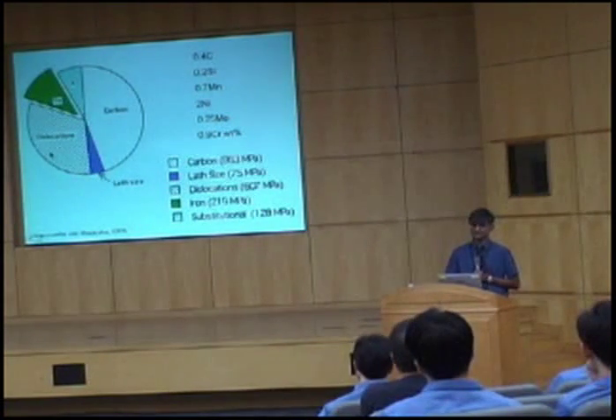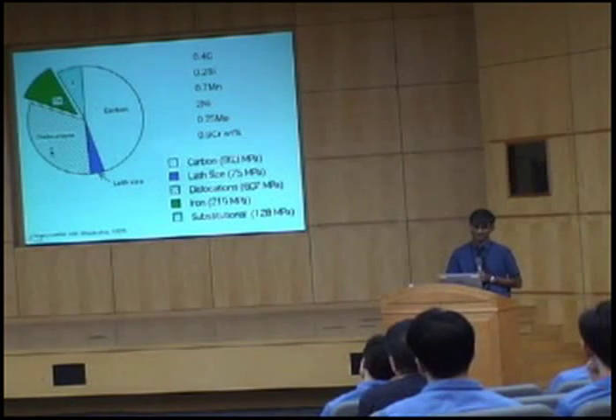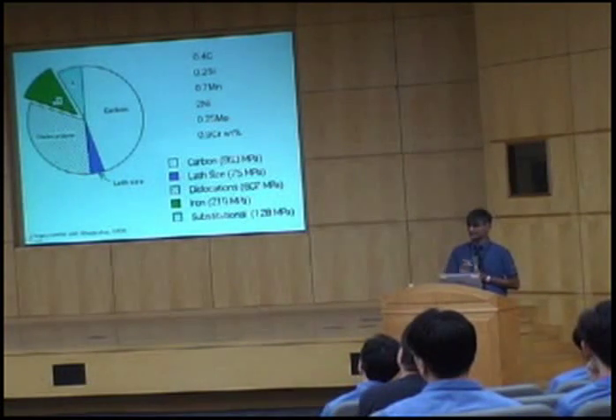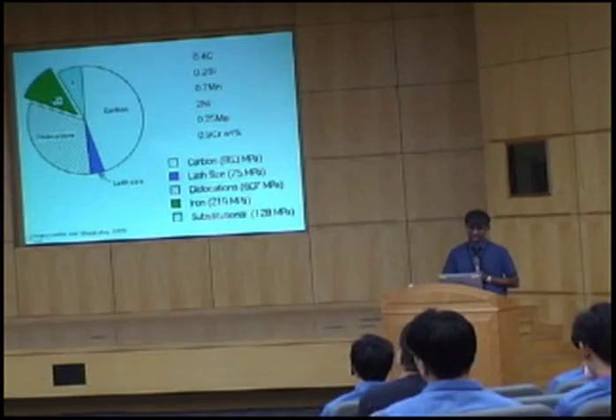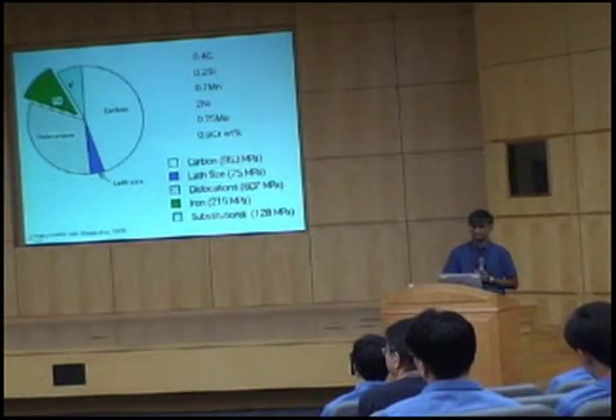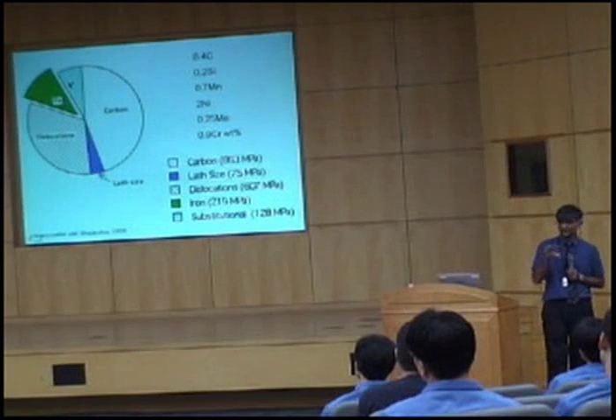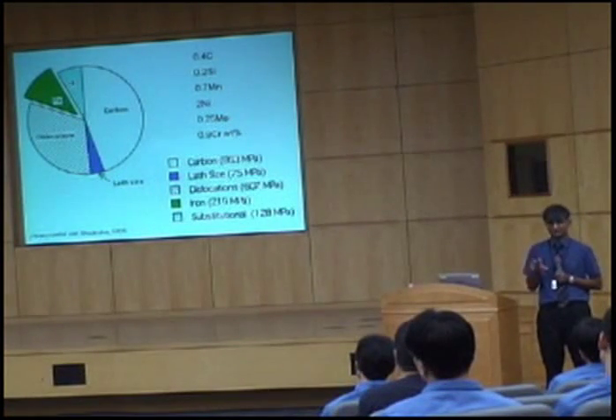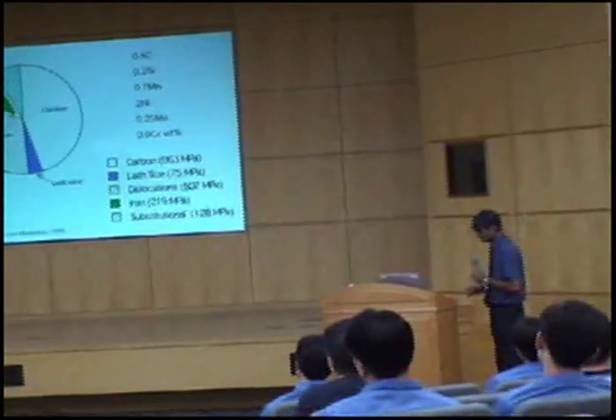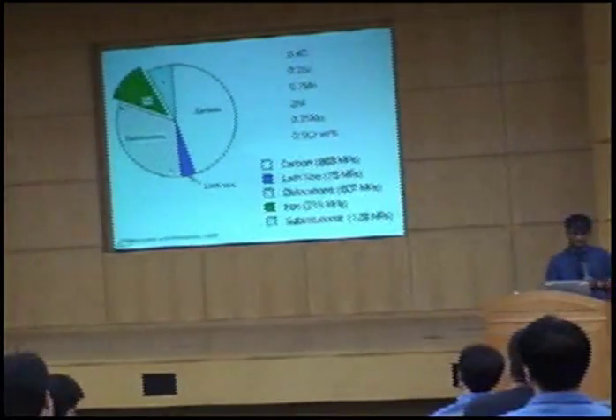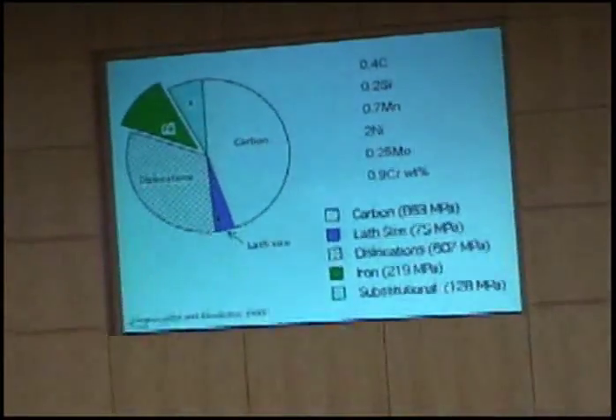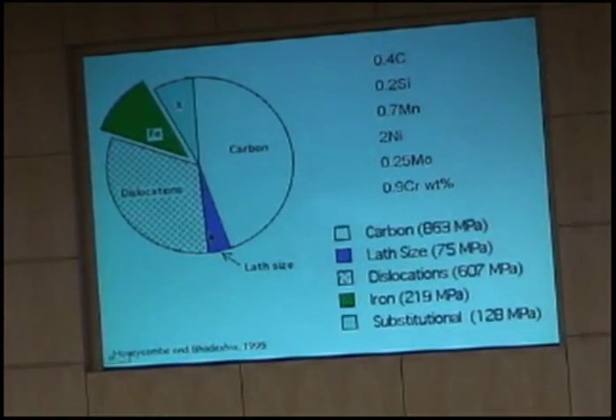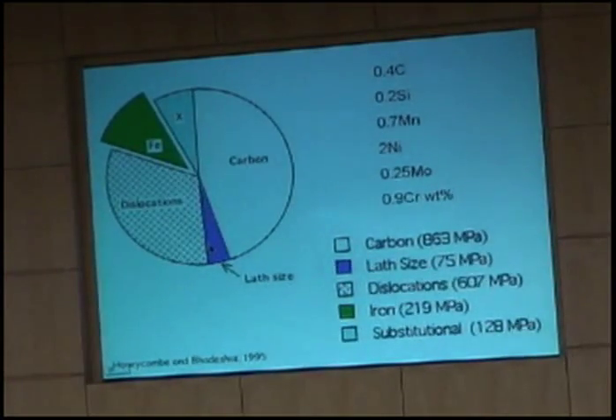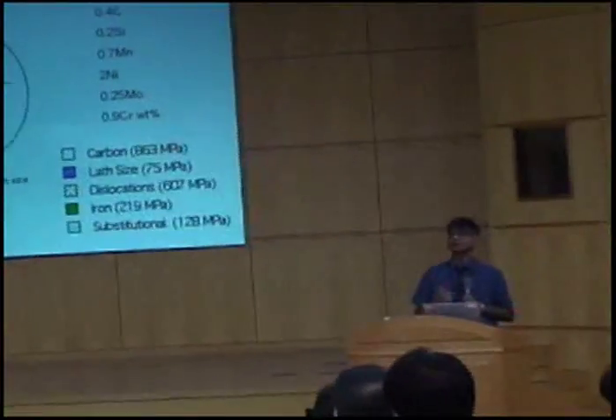Instead, the dislocation density makes a large contribution to the strength. And this is the strength from pure iron without any microstructure, because that still has a resistance to dislocation motion. And then we have our substitutional elements. So it's possible to look by calculation at the different components of strength and to engineer those according to need. This component of strength, if we reduce the thickness of the plate by a small amount, it increases dramatically. And later on I will show you that that can make the biggest contribution to the strength of bainite.